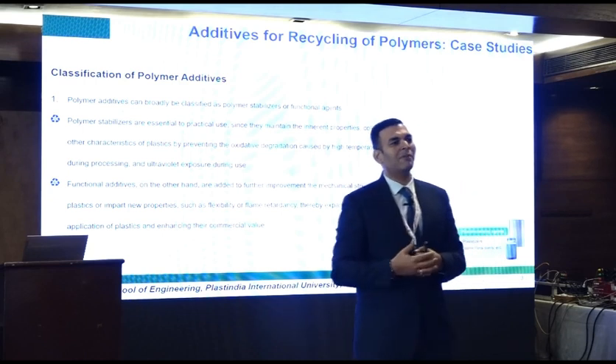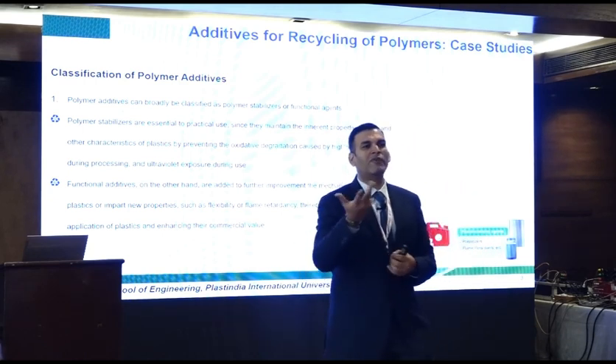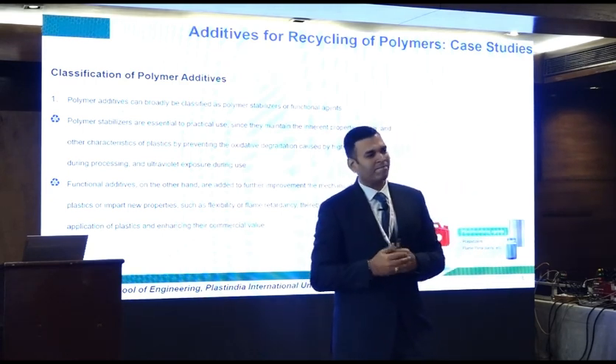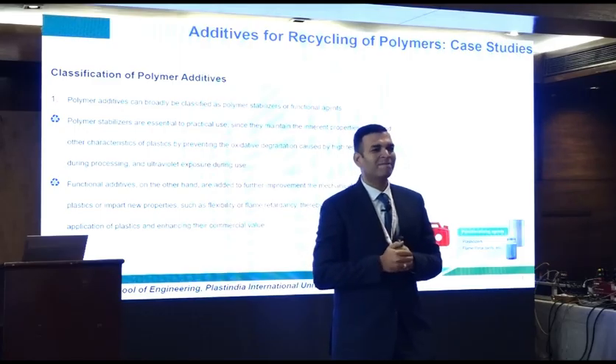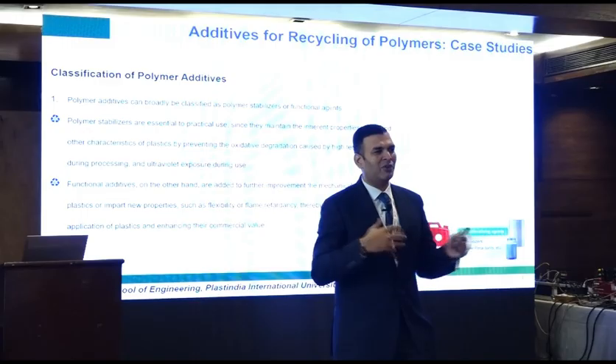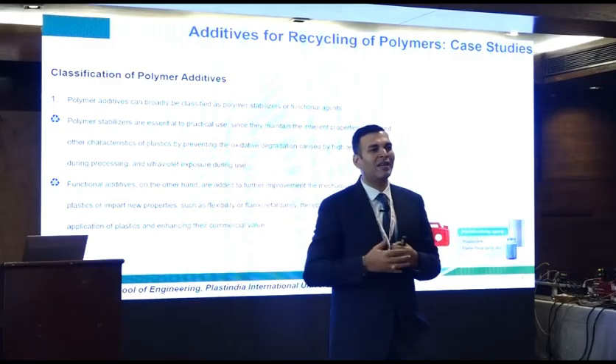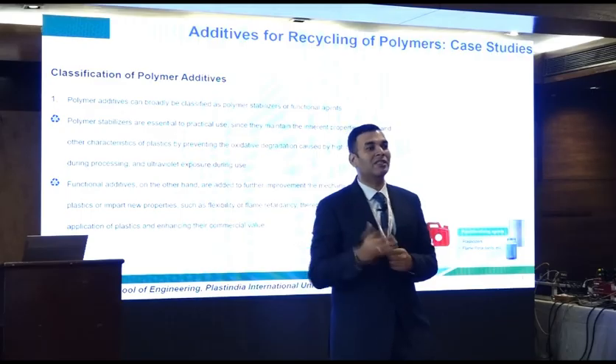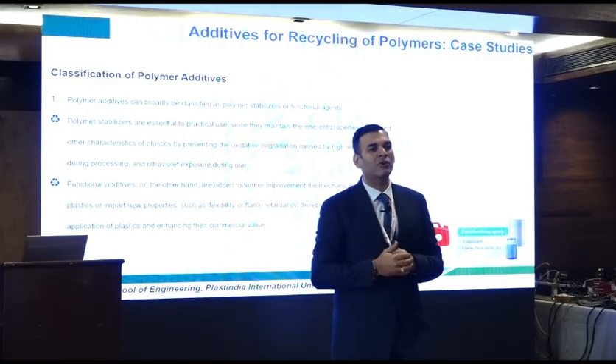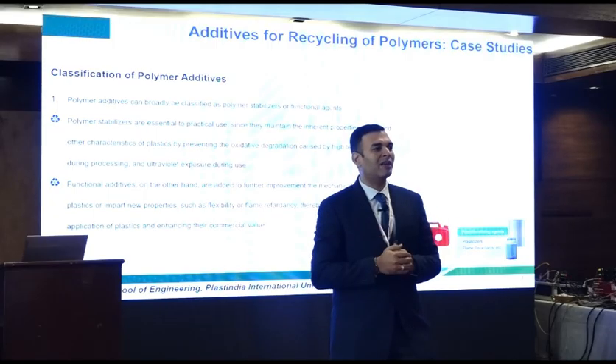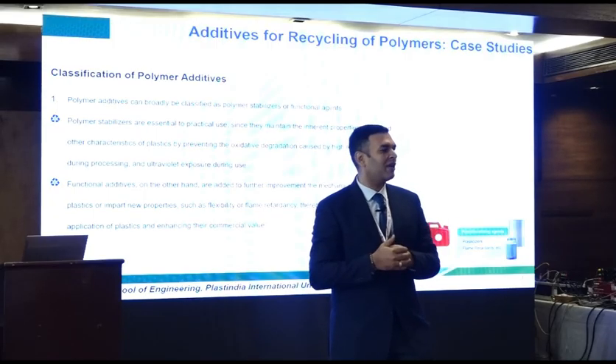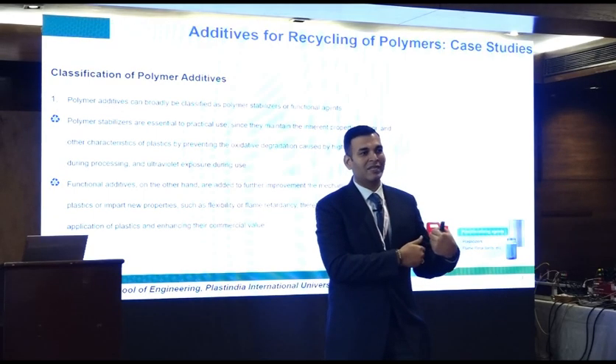The continuous service temperatures may require up to 150 degrees centigrade. Difficult to use, right? Polypropylene has an HDT of around 69 or 70, and then you add fillers into it. Certainly, definitely would not reach up to 150 degrees centigrade. People are doing research on heat stabilizers where polypropylene can be taken up to 150 service temperatures as well. So the day may not be very far where we are practically talking about polypropylene used inside the hood as well.